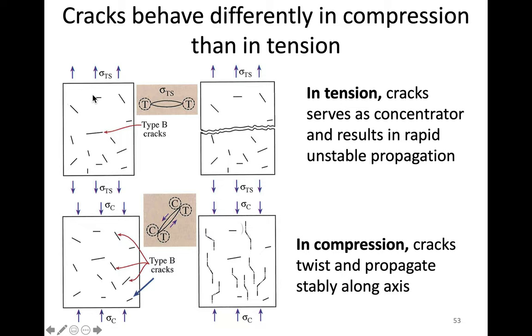When we apply stress here and here, it's basically trying to open up this crack, and that puts tensile stress on these edges. These are stress concentrators, so all of the stress concentrates on these locations, allowing it to break and unstably propagate throughout the material.